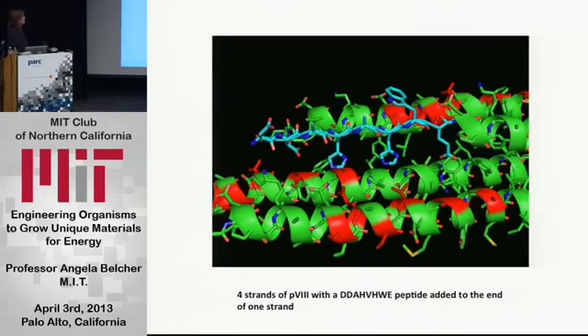And so, again, for the biochemist fans, I know there's some of you out there, these are some of the amino acids. This is the reaction vessel where this happens. These are the amino acids that not only do you have the amino acids along the individual alpha helix, but they form a 5-fold symmetry and they self-assemble. And you have the chemistries of these overlapping sequences to play with. And so not only are you thinking about engineering on a single strand, but you're thinking about strand-strand interaction and using those as a way of controlling materials.